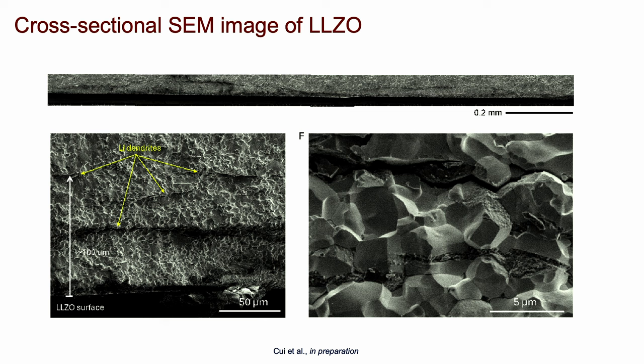Looking at where the cracks are forming, we see that cracks are forming both between the LLZO grains, which are sites that others have seen lead to failure, but also through the grain. So it doesn't look like there's a huge difference there.